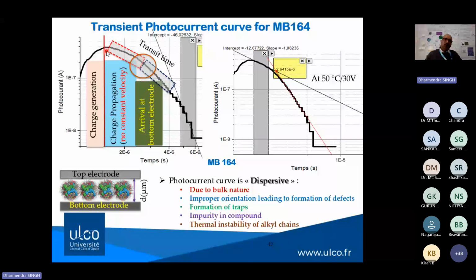This part should be constant. If the charges have a constant velocity, you will get a plateau. But if it is not a plateau, if it is dispersive, then this means there is no constant velocity of the charge carriers, and then the charges arrive at the electrode. As I have shown, these photocurrent curves are dispersive, and there are certain reasons behind that, due to the bulk nature, maybe impurity or thermal instability.